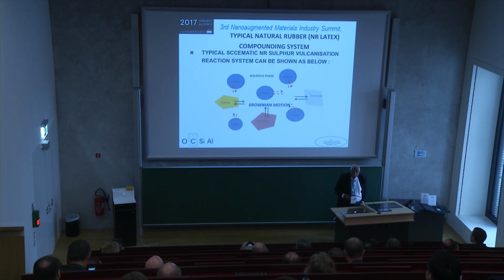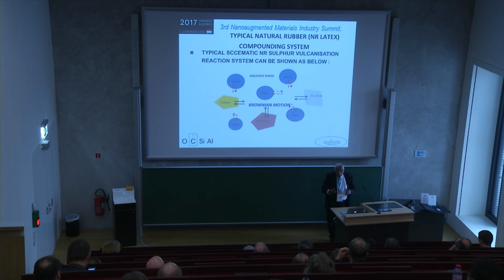In the pre-vulcanization process, we are adding, in the aqueous phase, sulfur, accelerators, and activators, and incorporating them into the latex. As you know, you have Brownian motion, and so you have constant collision of the particles, and we have the absorption of these chemicals, which are predispersed, into the latex particle. And once it gets into the latex particle, these are low temperature, and we can do it at ambient temperature,